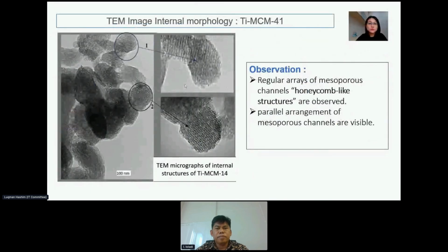The internal microscopic structures of this modified MCM41 were analyzed by using the TEM analysis. So the image clearly shows the parallel arrangements of these mesoporous channels for the modified support, and it is present in the form of these honeycomb-like structures, right? So based on the figures here, there are no visible titanium particle dispersions in this TEM image, which indicates that there is a well dispersion of this titanium species within the framework of the mesoporous silicate structure.